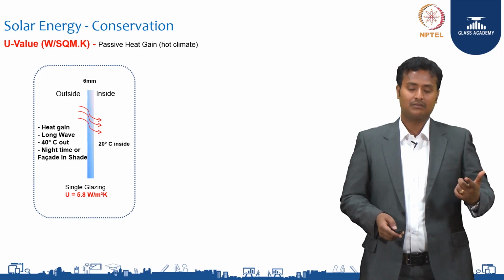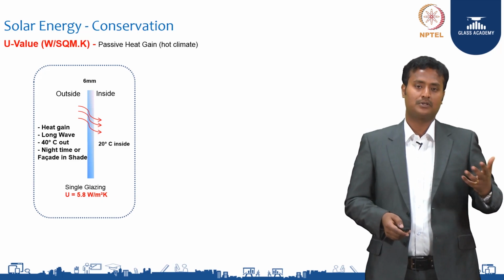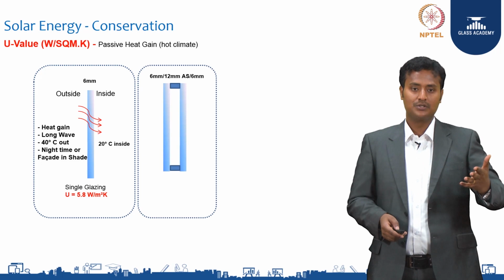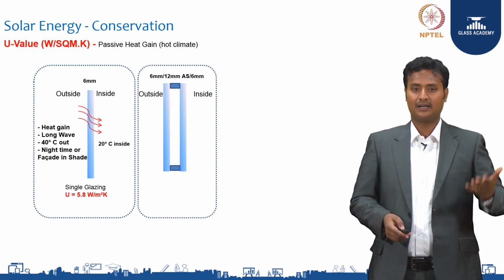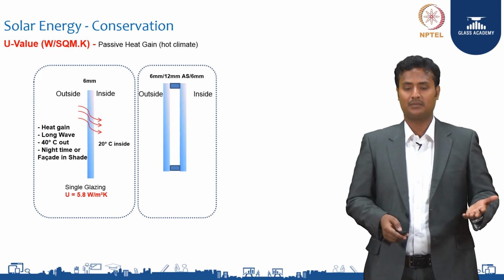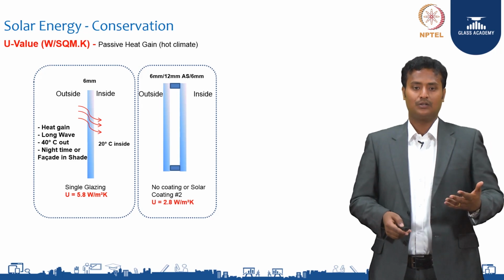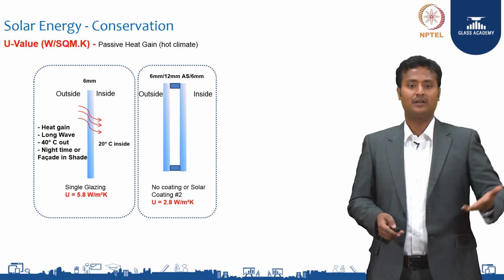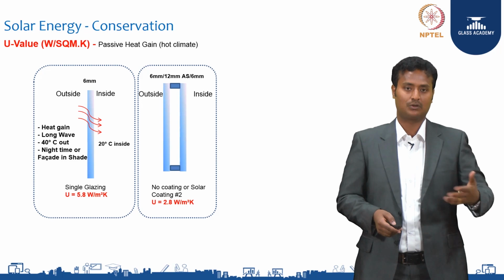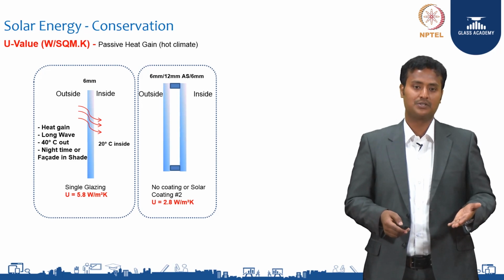A single glazing has a U value of 5.8 watts per meter square Kelvin, whereas if you use a double glaze unit like 6 mm, 12 mm air gap and 6 mm, you will get a U value of 2.8. It can be reduced even further with the help of solar reflective coated glasses if you use them.